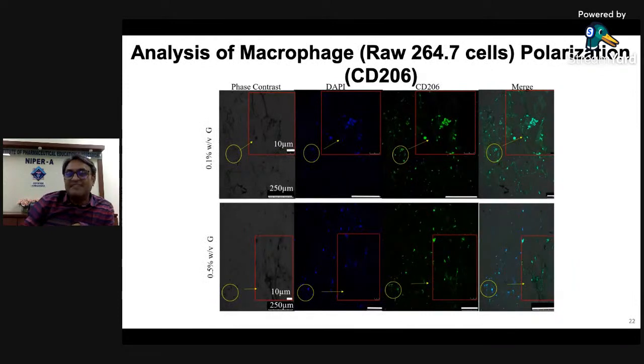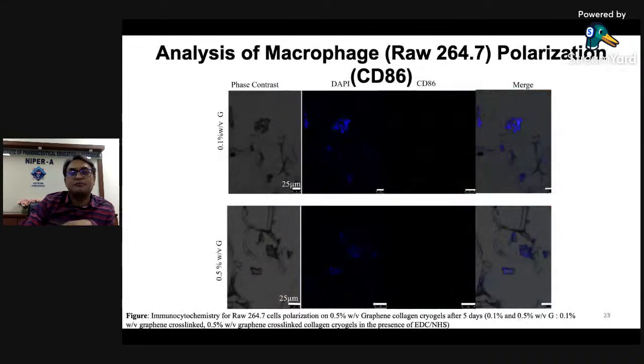We further tested it in immunohistochemistry, and we found similar results with CD86. You see very diminished CD86, meaning the M1 polarization is very less.